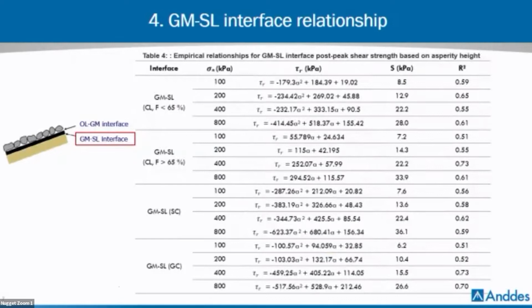And what about peak shear strength for soil liner with geomembranes? Well, the empirical relationships were not defined due to a low correlation coefficient and a high standard deviation. For that reason, we don't show formulas for peak values for this kind of interface.